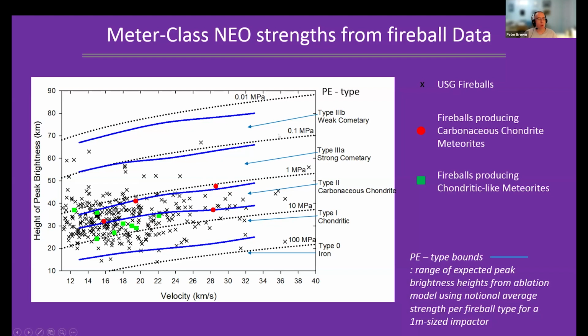And what I'm showing is just the dynamic pressure ranges. So this is the dynamic pressure, 1 megapascal, 0.1 megapascal, given this height and this velocity. And what you see is that most objects penetrate down to of order a few megapascals. Some get down to even 10 megapascals. There's a few that seem to break up extremely high in the atmosphere at a few tenths or even less of a megapascal. And we also have meteorites here for comparison. That is US government sensor fireball measurements for which meteorites have been produced. And we can map onto this chart our estimates of where the different PE classes fall. And they're basically consistent with the fireballs that have produced meteorites.